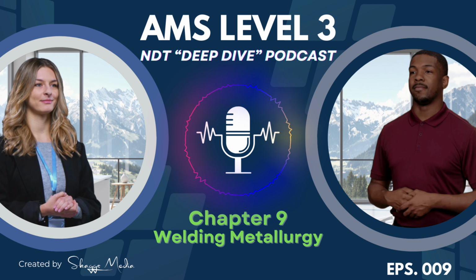stresses. Which causes hydrogen cracking, also called underbead cracking or delayed cracking. Precisely. Underbead, because it often initiates in the HAZ right under the weld bead. Delayed, because it might not happen immediately. It can take hours or even days for the hydrogen to diffuse, concentrate, and build up enough pressure to cause a crack, especially if the material also has a brittle microstructure like martensite.